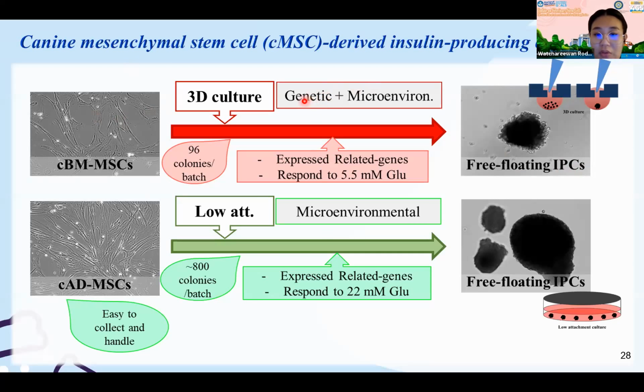For the bone marrow, we found that the integration protocol of the genetic with the microenvironmental method can get a good colony which expresses the pancreatic related gene and responds to the glucose when we challenge them, like incubating them with the glucose solution to see whether they can produce insulin or not. We found that they can respond to the low concentration of glucose at 5.5, which is equal to around 90 to 100 milligram per deciliter, the normal glucose level range in normal people.